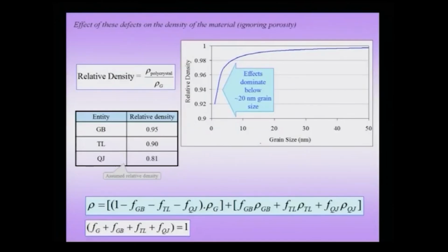Now, what effect does this have on the density of the material? We already noted that the bonding and the coordination number are smaller in the grain boundary or the higher order entities as compared to the bulk. Therefore, this is going to affect my density, and as expected this effect is going to be prominent at about 10 nanometers or of that order.